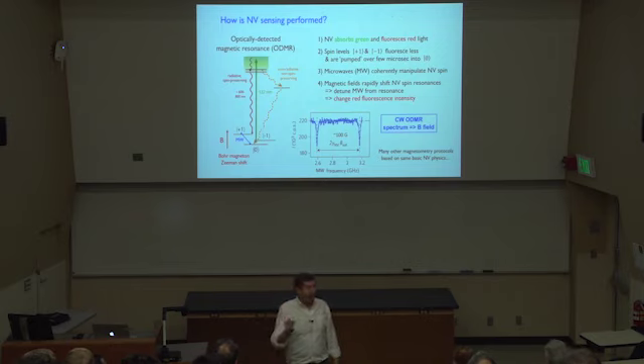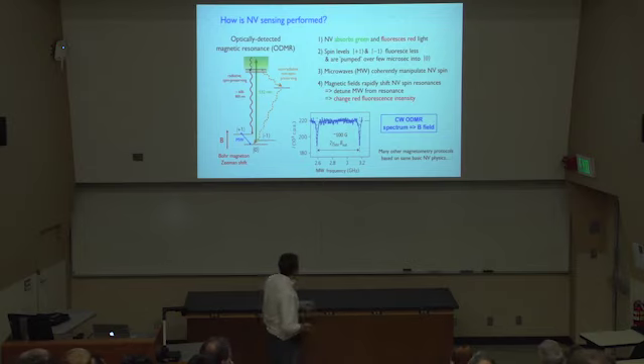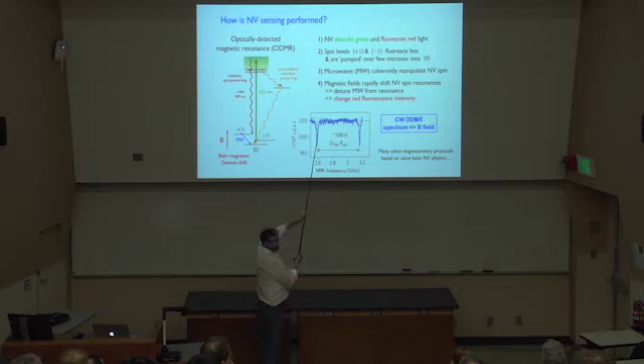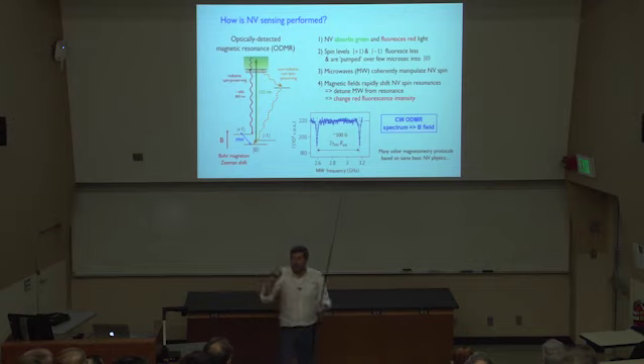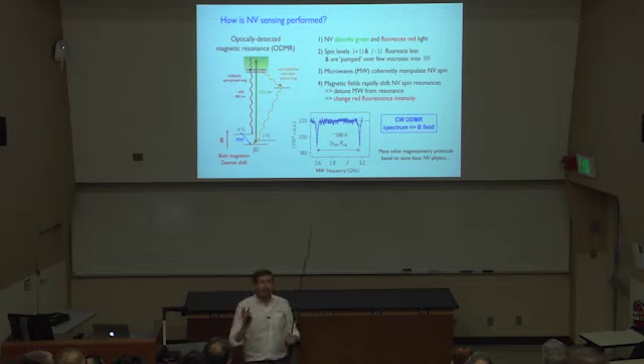Typically what's going on, and almost all the results I'm going to be showing you as we move forward, we know what the magnetic field is approximately, and we're looking for tiny either temporal or spatial variations in the magnetic field around some value. So we might sit on the side of a resonance and look for, as a function of either time or position or both, how the intensity of the signal is going up and down based upon slight variations in the local magnetic field. Right? We're not going through to do the whole complicated thing usually, except for demonstrations.